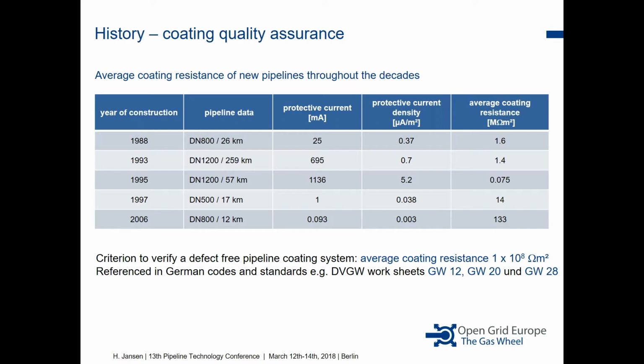And in 1997, we first carried out so-called current drainage tests on pressure test sections. We injected the current, measured on and off potentials and measured the current, and we gave certain threshold values in order to find, with this very quick current drainage test, larger coating defects on these pressure test sections.